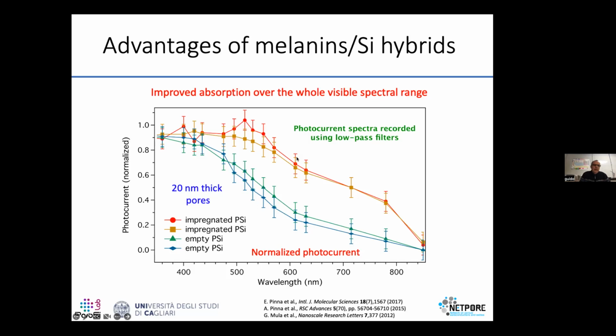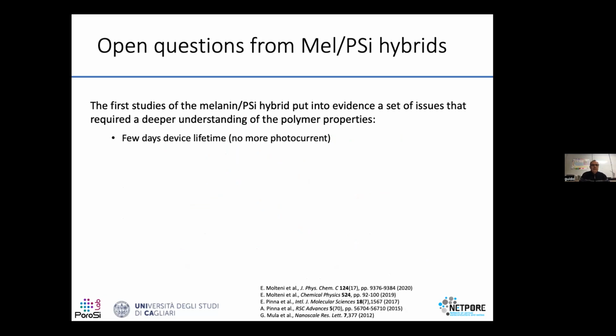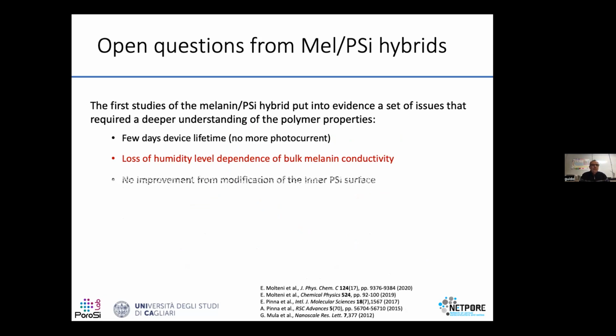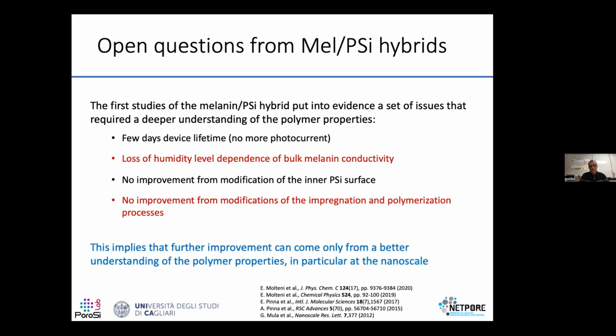And that is proof that your absorption rate has been improved with respect to empty silicon. And if you compare the absolute values, you can see that with impregnated porous silicon, you can have photocurrents which are even 2 orders of magnitude higher than on empty porous silicon. So the system works, but it has some drawbacks. First is that the device lifetime is just a few days. You lose the humidity level dependence, which is typical of melanin conductivity, which increases with increasing humidity level. And you do not have real control over your system by modifying the inner porous silicon surface or modifying the impregnation or the polymerization process. And this is important because it proves that the only way to understand what happens to your system is to understand what happened to the polymer. But this is a problem in the sense that polymers at the nanoscale are very difficult to characterize.